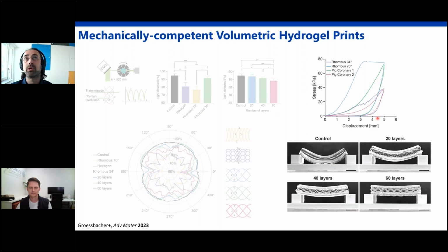in the burst pressure, it's more of a punctual part, usually at the junction between the gel and the connecting system. When we look at the circumferential stress or the tensile assays, what we see is that the first thing that fails is the gel itself. So the gel is the weak component here, of course, of this composite. We see a crack propagating into the gel, but we don't really see delamination from the fibers. That being said, we haven't seen it, but we cannot exclude it.